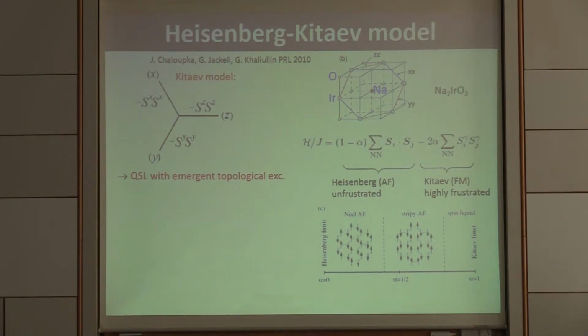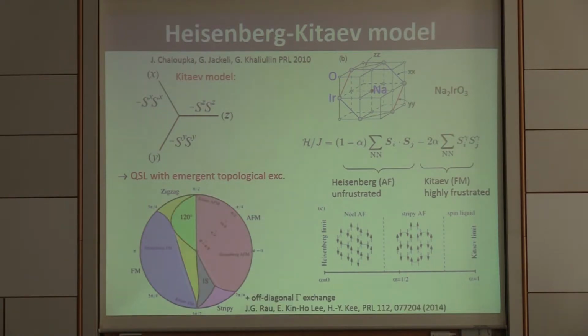And in their first scenario, they considered a ferromagnetic Kitaev-type term and additional antiferromagnetic Heisenberg exchange, which could, for instance, come from the direct overlap of the extended 5d shells. And they found that the Kitaev spin liquid is stable unless a certain threshold of additional Heisenberg exchange comes into play. Later, it was recognized that we also have to consider off-diagonal so-called gamma exchange, which mixes here, for instance, in these 2 sites, also an exchange between x and y component on 2 different sites.